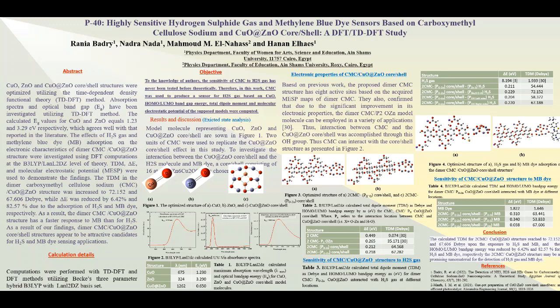The sensitivity of CMC copper oxide zinc oxide core shell structure to H2S gas and to methylene blue dye. As we can see from Figure 4, there are different positions for the interaction of the H2S gas and methylene blue dye with CMC copper oxide zinc oxide core shell structure. Table 3 and Table 4 present the obtained values of the total dipole moment and HOMO-LUMO band gap energy for the CMC core shell structure interacted with H2S at the different positions and with the methylene blue dye at the same positions. It's clear that the values of total dipole moment and HOMO-LUMO band gap energy differ by changing the position of the interaction, which means that the proposed structure of CMC and core shell structure is more sensitive for the H2S gas and methylene blue dye.